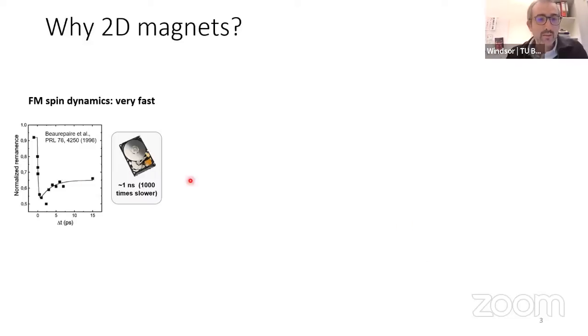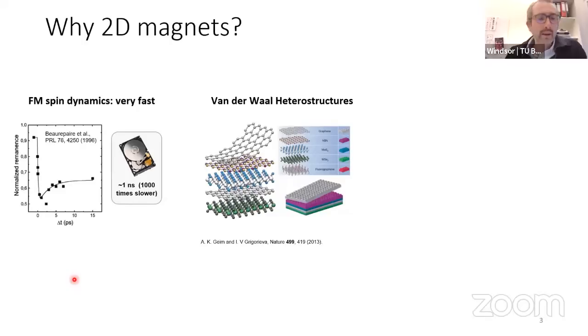Here I'm showing a comparison. Most hard drives work at around a nanosecond timescale. I think the fastest switching is around 250 picoseconds. I might be off now. There's probably newer work. And this is the seminal paper from 1996, where you can see this initial very fast demagnetization of metallic nickel.